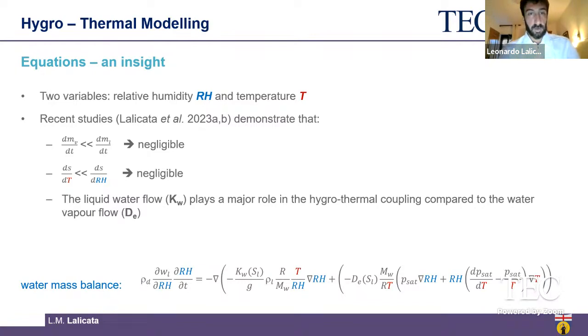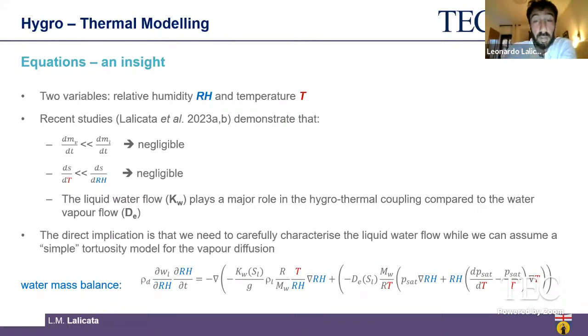The other result of our preliminary investigation is that the liquid water flow, which is described by these parameters Kw, and this depends on these parts of the equation here, plays a major role in the hygro-thermal coupling compared to the water vapor flow, which is the diffusivity tensor in here. For us, this means that we need to carefully characterize the liquid water flow, while we can assume, without any significant error, a simple tortuosity model for the vapor diffusion. And by simple, I mean that you can use standard literature solutions.